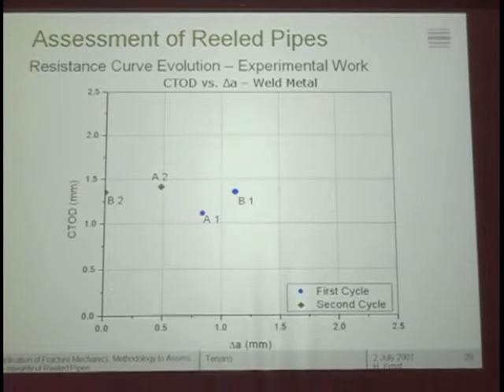This is the first of the two materials that I show you, CTOD versus crack extension. A1 is what you have in crack extension for sample A in the first cycle. You have applied a CTOD of about 1.1, and then you apply a CTOD of about 1.4, and you get this much of crack extension, A2.